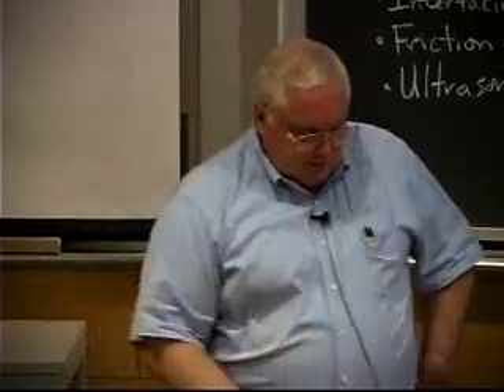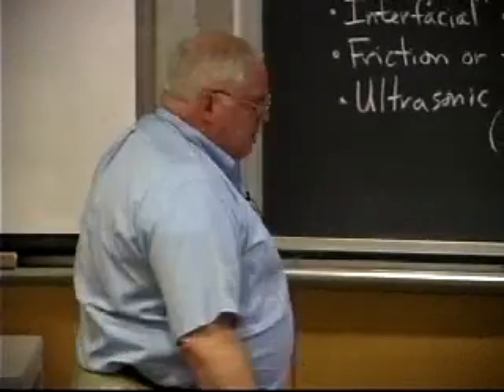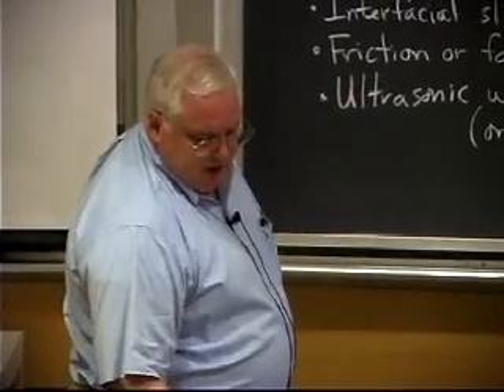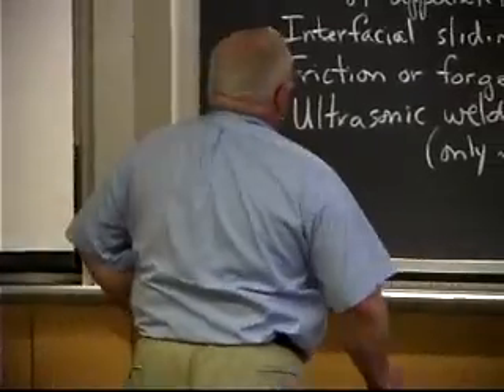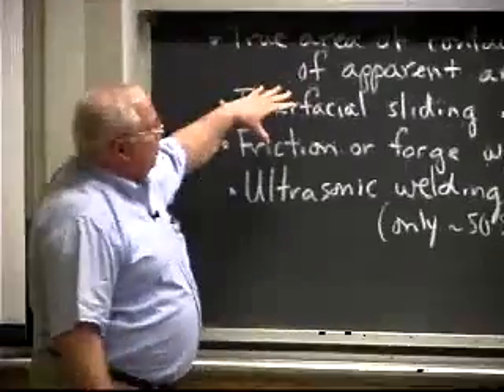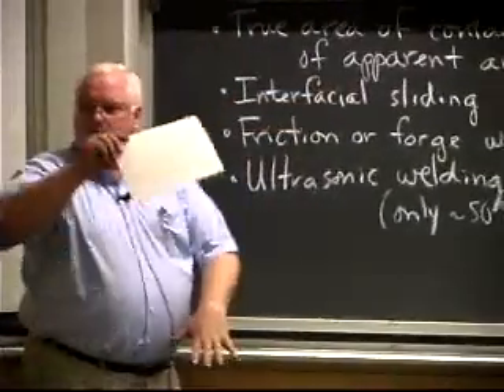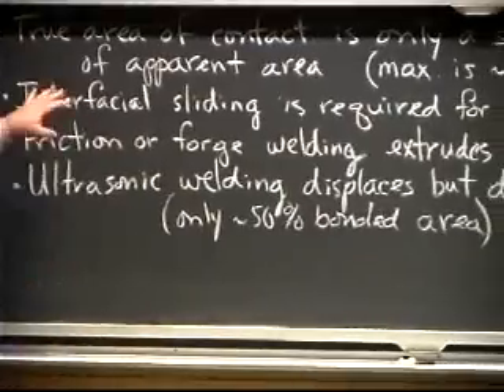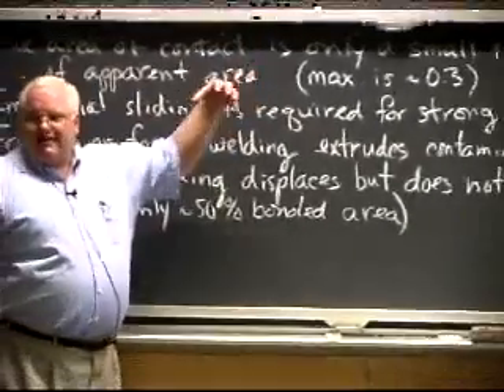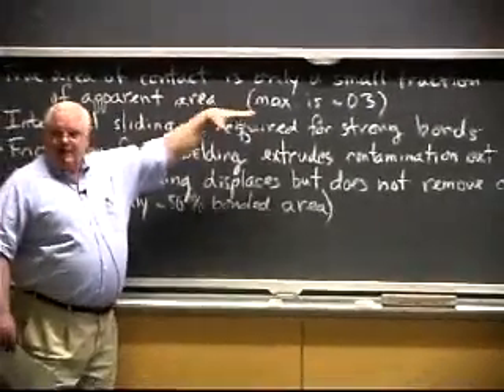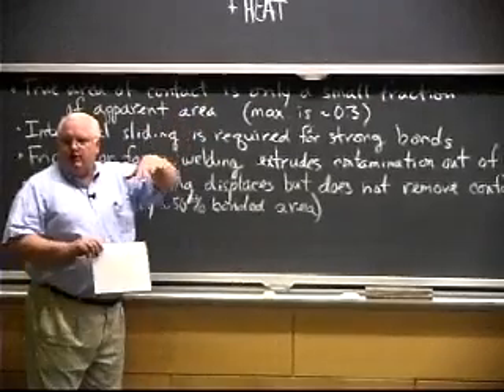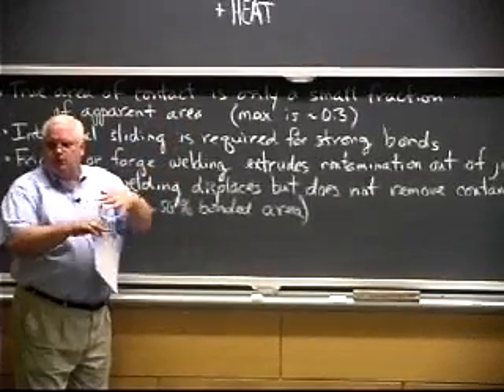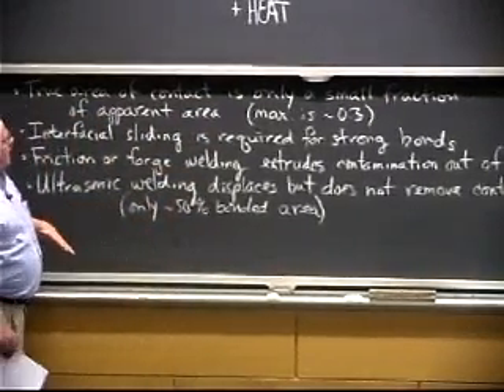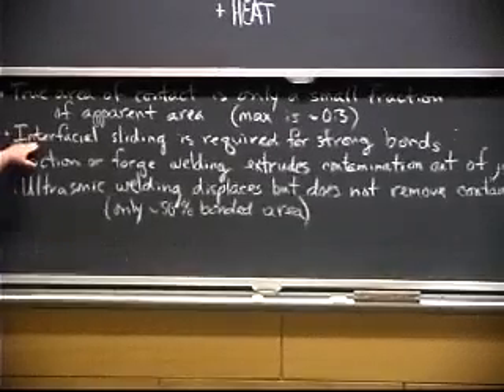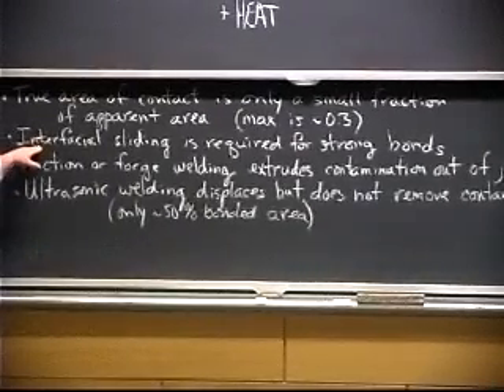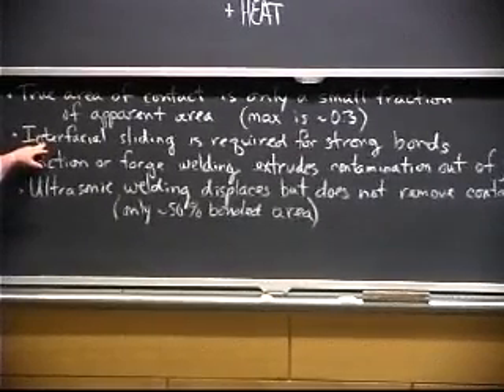I wanted to go back to friction welding and cold welding. We said that true area of contact is only a small fraction of the apparent area, remember, because the mountain peaks come together, but they have a certain indentation hardness strength. And even if you get to the point where the whole thing is starting to flow, just straight normal forces won't give you true 100% area of contact. You need interfacial sliding to get that, to break down those mountain peaks, to plow them away, and to get rid of the contamination.